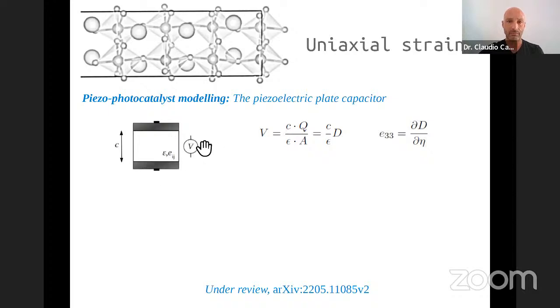So we have here a plate capacitor, and here we have a dielectric material. Let's imagine that this material is not just dielectric, but also piezoelectric, and that it doesn't have a spontaneous polarization. So if you don't squeeze it, if you don't apply ultrasound, the polarization is 0, and the potential drop between these two plates is 0. Because, as everyone knows, that potential drop is equal to this relation here, where C is the distance between the plates, epsilon is the electric constant, and D is the electric displacement, which is basically equal to the surface charge density on the plates.